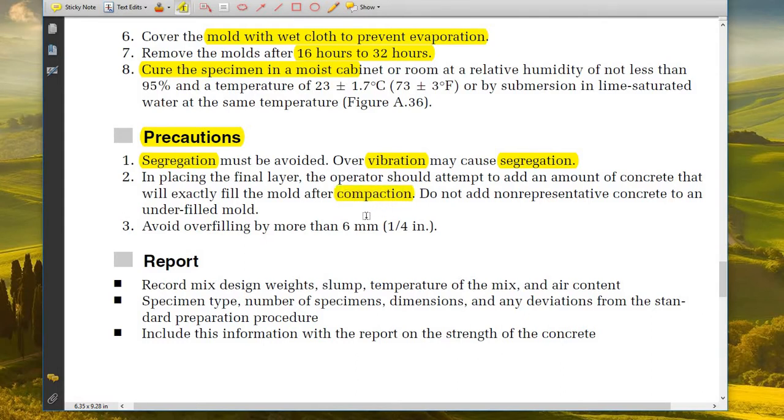When you strike it off, you want the surface to be smooth. Do not add non-representative concrete to an underfilled mold. Avoid overfilling by more than six millimeters.